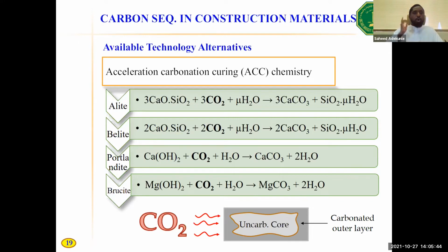Because if you pump CO2 under pressure or under special conditions to the cement hydrate, okay, CO2 will go back into this hydrate and bring out calcite, which was the original raw material that was broken down thermally. Okay, and this process is exothermic. It releases heat. If you look at the belite itself, belite also can combine with CO2, not in the original belite form, but it can combine with CO2 in the hydrate form.